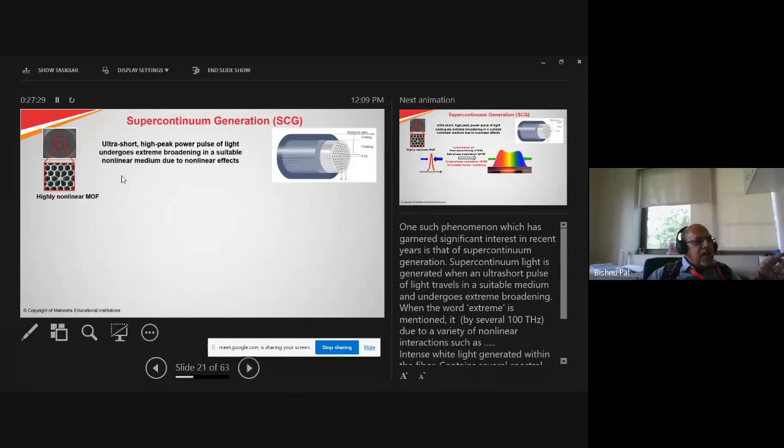So overall, the average refractive index of the surrounding region, which constitutes these holes, is pretty small because the glass is a very small fraction of it, and at the center you have glass, so you get a high numerical aperture fiber, and as a result you can confine light to the small solid area very strongly. So you get nonlinear optical effects very easily in such a structure.